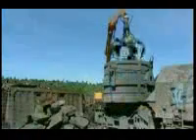A carefully selected blend of iron and steel scrap is lifted by overhead magnetic and hydraulic cranes into an electric arc furnace. The scrap steel blend is then melted in the furnace at an intense 1700 degrees Celsius. Burnt lime is added to form what is known as slag. The slag creates reactions within the molten metal and impurities are removed into the slag.